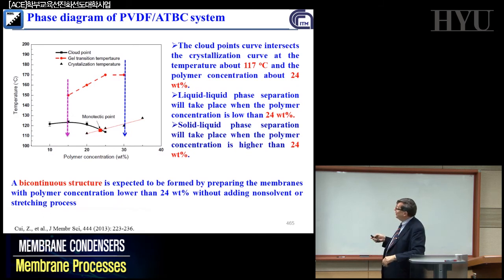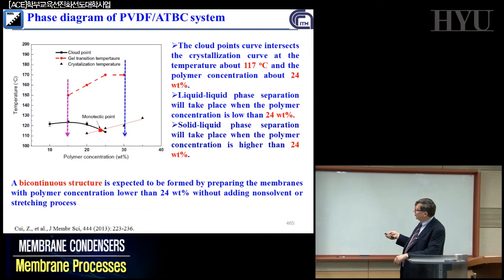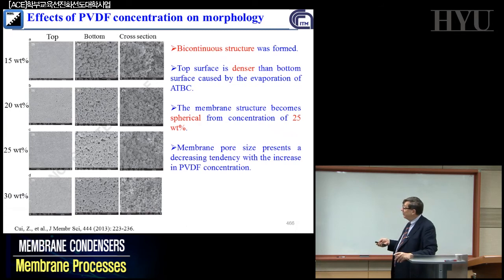So you have to start from studying the cloud points, crystallization problem, and to build up this kind of phase diagram where you know everything about cloud point, gel transition temperature, crystallization temperature, and so you can predict that at a certain concentration you can have liquid-liquid phase separation, and at another concentration higher than 24%, you will have solid-liquid phase separation. And if you have these different concentrations, the final morphology of the system will be very different. Because in one case, you will have a bicontinuous structure at concentration lower than 24% with this kind of solvent, and at higher than 25%, you will have a spherical final morphology in the system, and this will give totally different performance.